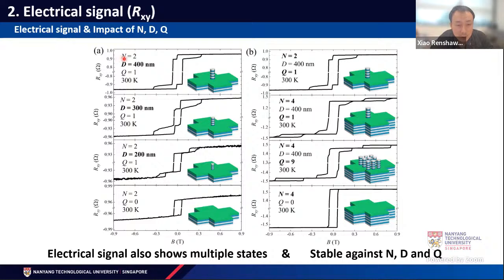I can see that by playing with n and playing with the d, which is diameter, q, we can have different magnetic features or different magnetic transitions. It looks a little bit cloudy, but the signal is, first, we have different magnetic transitions, we are able to capture different magnetic transitions in electrical measurement, and it's also stable against the different n, d, and q. Basically it means we play with the n, d, and q, we always can get these different magnetic states.